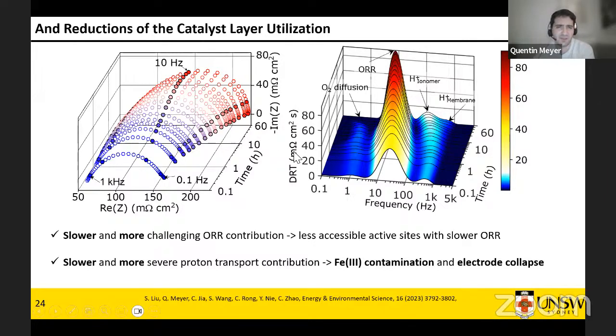Looking at it with DRT, we get quite a different picture. So again, this is exactly the same data. There are two different ways to analyze it. We have proton transport in the membrane. It's present from the very beginning. Then the two split into proton transport in the ionomer, so in the catalyst layer, and in the membrane. The ORR initially becomes much bigger and then slowly shifts towards lower frequency. And gas diffusion seems to basically disappear, which is a bit confusing.